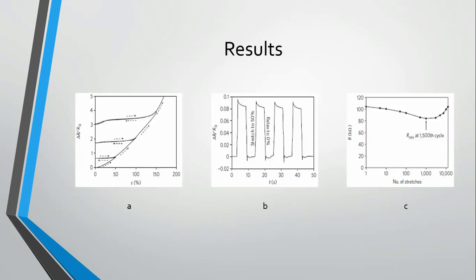From the results, we can see that the first figure shows the change in resistance versus strain for the film. When the film is strained, resistance increases and remains constant as strain is released. When strain is increased again, resistance remains constant and then increases when strain exceeds the value at which the strain was released before. Figure B shows resistance versus time in response to 4 cycles of stretching from 0 to 50%, and figure C shows resistance versus number of stretches over 10,000 cycles of stretching at 25%.